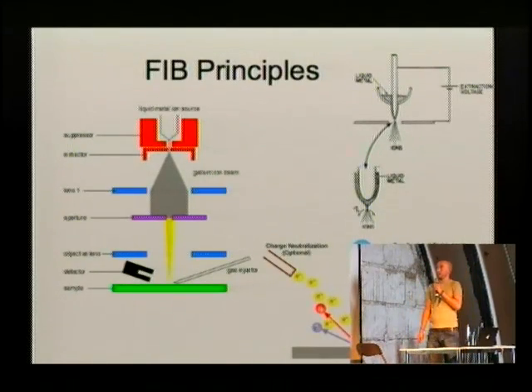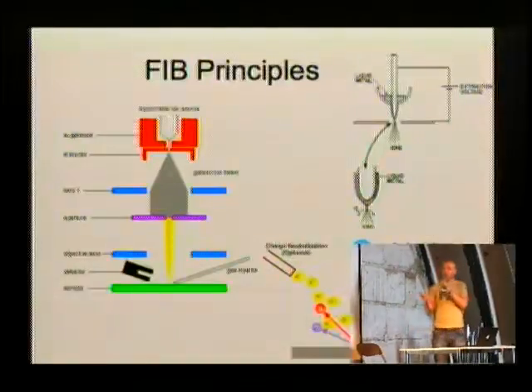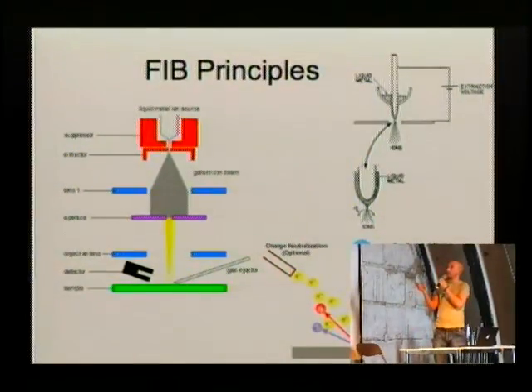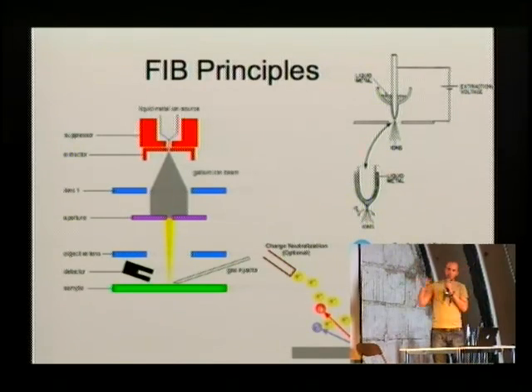The focused ion beam is pretty much the same. Instead of an electron source, you have a liquid metal, in most cases gallium. You have a small metal tip, and if you heat up the gallium slightly, it forms a thin film, and given that you have an extraction voltage, it just sprays off the tip of the needle.